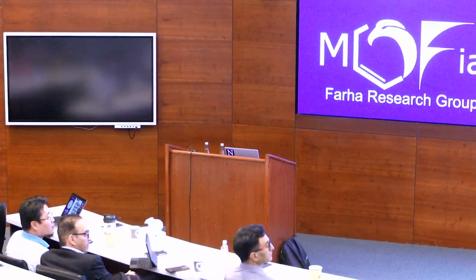All the numbers I showed you here, I didn't talk about that, but it's very crucial for you to make particles of different materials that are of similar size. Because the particle size and diffusivity, the smaller the particle size, the faster things can diffuse versus large crystals. So when we compare and contrast different materials, we try to make all these MOFs have similar particle size. Otherwise, your numbers will be all over the place.